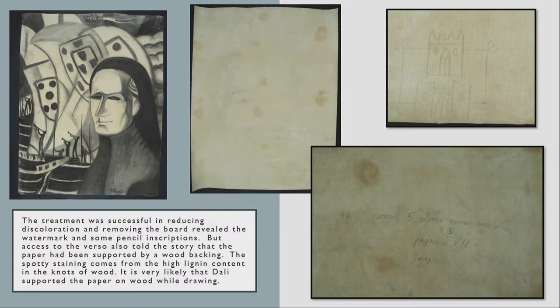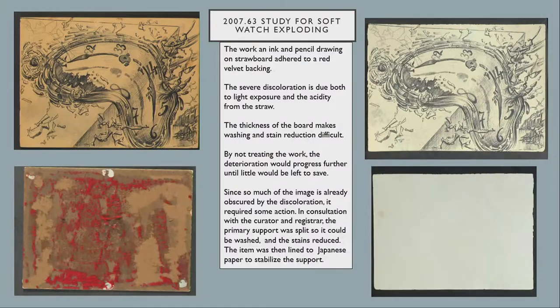But more importantly, from my point, these little splotchiness, this is where the knots of the tree, which have the most lignin, seeped into the paper. And what does that tell us? It tells us that Dalí, when he made this sketch, most likely had it up against a piece of wood long enough that the lignin stained the paper.